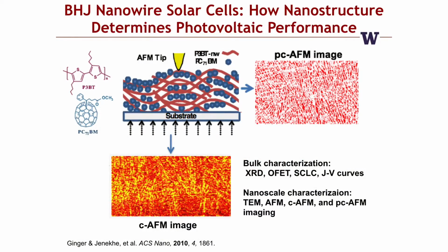We have used this approach a lot to try and do fundamental studies, particularly in collaboration with my colleague David Ginger in chemistry at University of Washington, where we were able to combine bulk characterization techniques with nanoscale characterization techniques such as photoconductive AFM or conductive AFM to really look at the nanoscale when you shine the light on the active layer and you are generating electrons and holes, watch where the holes are going, where the electrons are going. And we have extensively used this way of controlling the morphology to try and get a handle on some of the fundamental aspects of these devices.